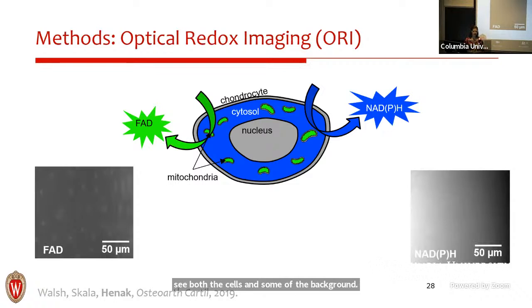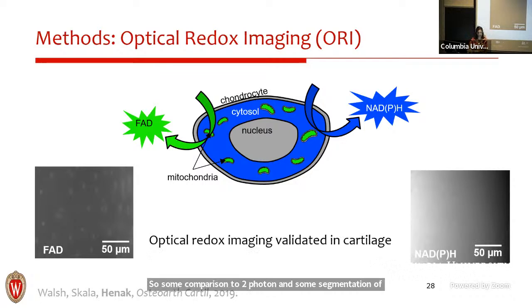We've done a fair amount of work to confirm that our signal is not just governed by the background. So some comparison to 2-photon and some segmentation of the cells to be confident in what we're looking at. And we've also done some validation where we use channel-specific inhibitors and confirm that when we inhibit OXPHOS, we do in fact see a decrease in the FAD channel.